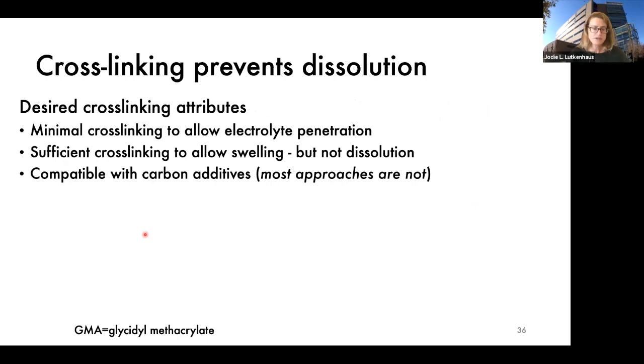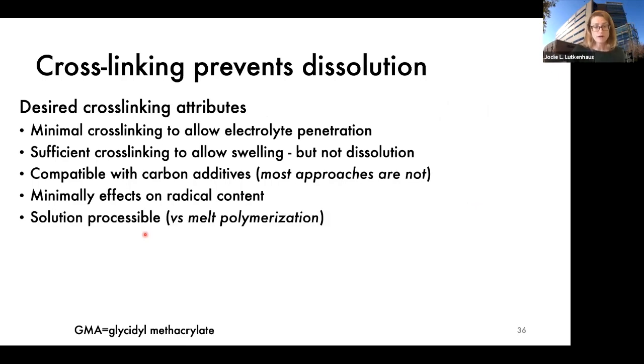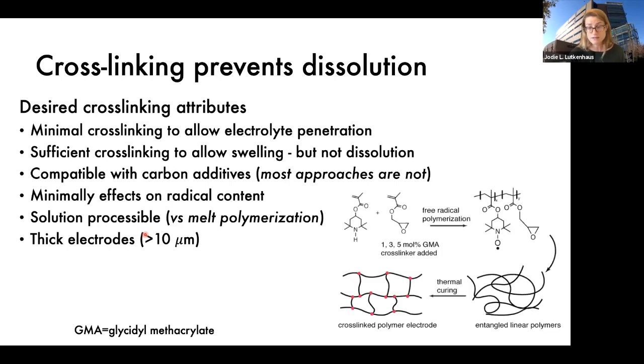Most of these materials in a practical battery have carbon additives to enhance the conductivity. So our cross-linking scheme preferably is compatible with carbon. Most approaches are not, actually. And then we want minimal effects on radical content. Cross-linking before has been done in the melt, but we don't want to mess with that. We want to use standard battery processing techniques like solvent slurry casting. And we want the electrodes to be thick, so we want it to be practical. So photopolymerization really isn't going to work for these requirements.